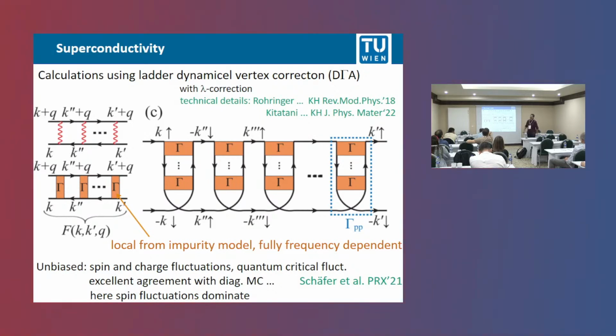You all know spin fluctuations from RPA at weak coupling, but now in these vertices gamma, we have included all the local DMFT correlations already. And because of that, we can now describe spin fluctuations also at strong coupling. There's a nice paper by Thomas Schäfer and others showing that these calculated spin fluctuations are in excellent agreement with numerical Monte Carlo results. Indeed, at first the Monte Carlo results differed, but then they did a better finite size scaling, and now they agree with the DΓA calculation.